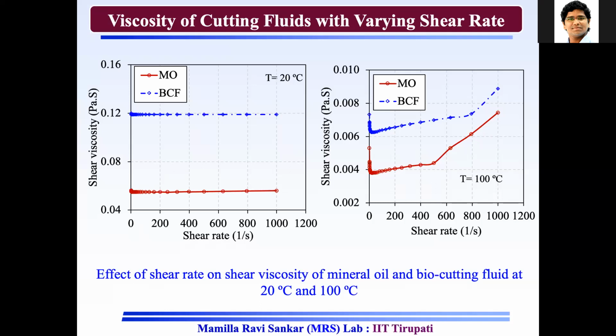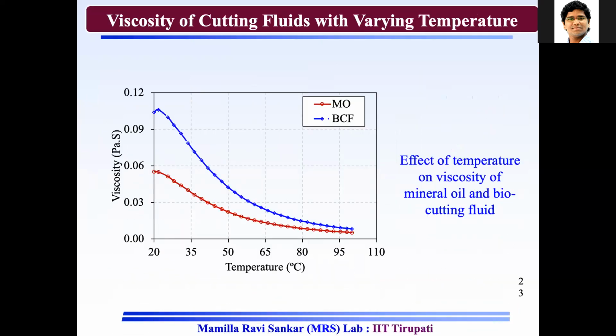As the temperature goes up, the water content will decrease, and it will be slightly difficult from the point of capillary action to impinge or penetrate into the chip-tool region. Otherwise, you can use high pressure coolant systems to penetrate in a much better way. You can also check how the viscosity is decreasing and other things.